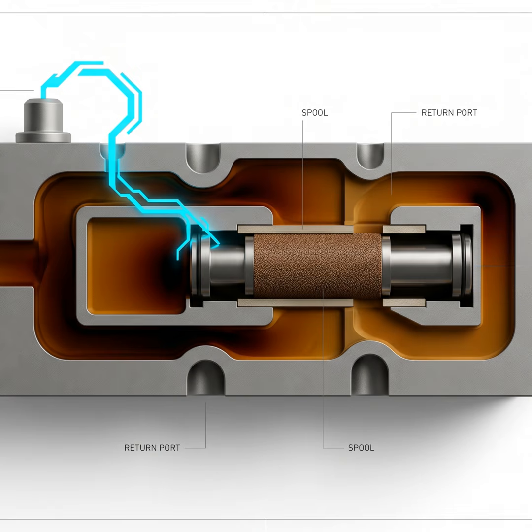They do clean things, but surface-active detergents and dispersants work by aggressively competing for the surface area of a metal. If you put a heavy detergent into a hydraulic system, it will certainly scrub the varnish off the servo valve. Oh, problem solved. But it will simultaneously scrub away that crucial ZDDP anti-wear layer we talked about earlier. Oh, no. The detergent molecules fight the zinc molecules for access to the steel. You would successfully solve the sticking valve problem, but you would immediately destroy the pump through massive metal-on-metal friction because you removed its protective shield. Oh, wow. So you cure the varnish but immediately kill the machine. That is a terrible trade-off.